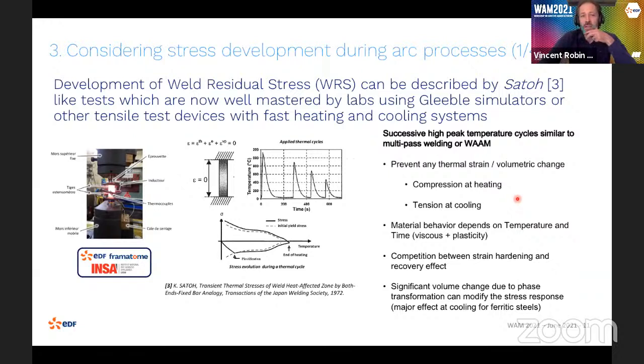It consists in using a round bar specimen, so it's a uniaxial test. And this round bar specimen is submitted to a realistic thermal cycle, fast heating and fast cooling. And we monitor the response of the material in terms of stress, so that we may have the stress evolution of the specimen during heating and during cooling. And because you prevent shrinkage or thermal expansion, you have compressive stress at heating and tensile stress at cooling.